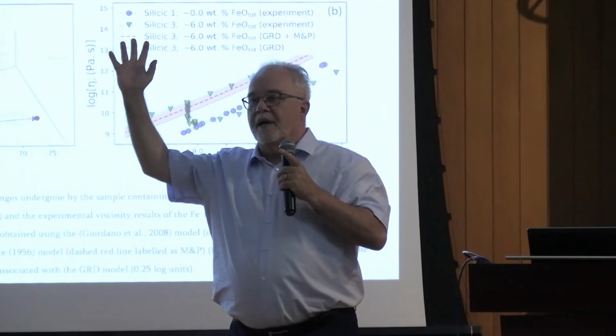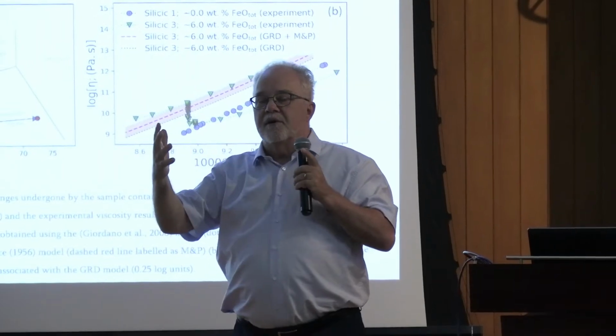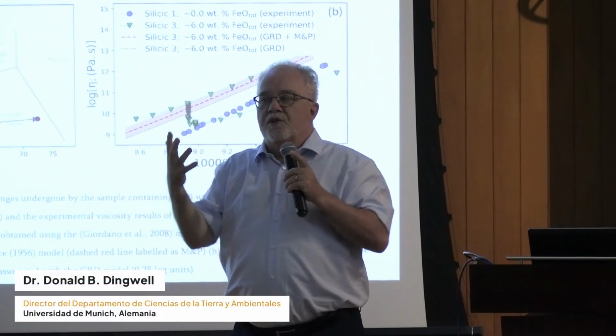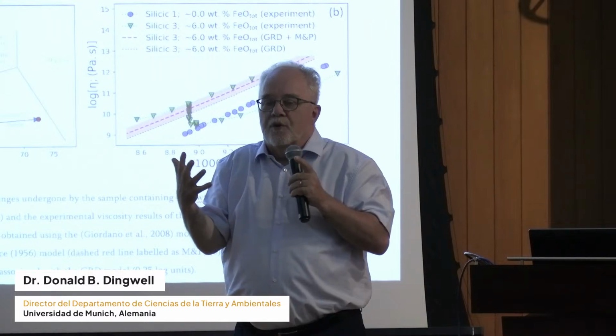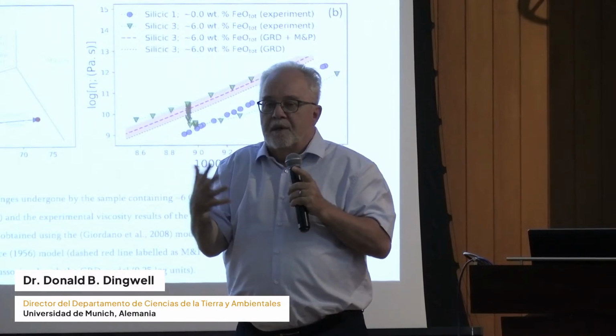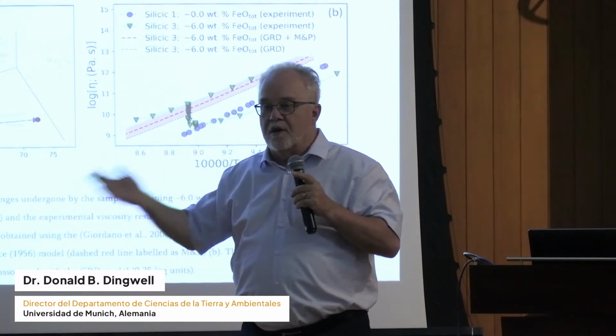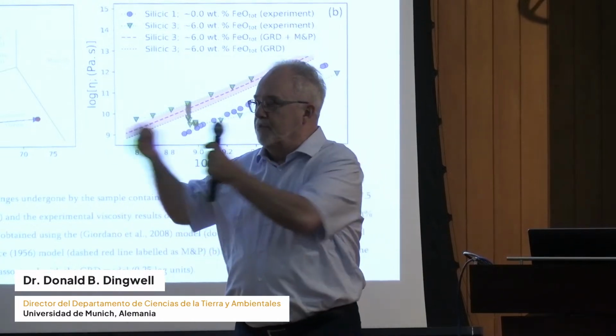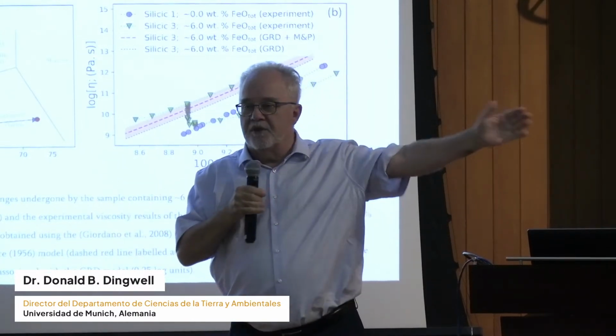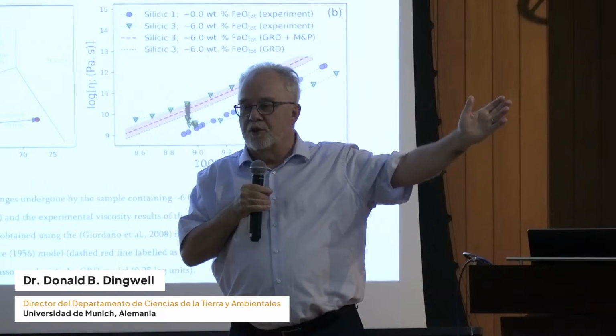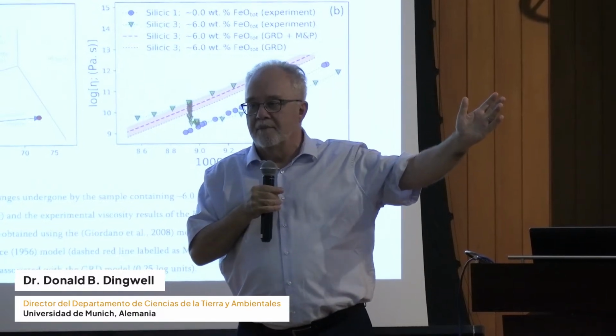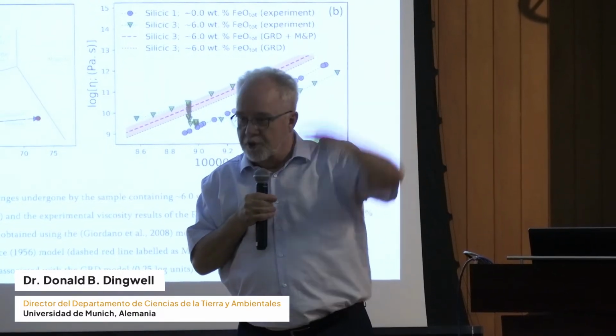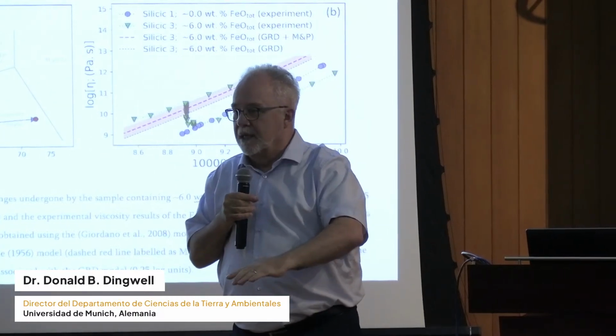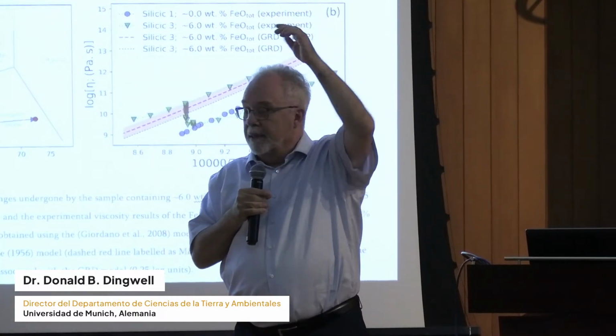Maybe you've sucked all the water out by decompression, bubble growth, fragmentation. The rest of the material is sitting there. The crystallization conditions that were inherent to it are gone because you've removed the water, you've changed the pressure. Suddenly it's jumped sideways with respect to its phase diagram, and it's perhaps undercooled by hundreds of degrees suddenly because the water left. And the water suppresses the liquidus, you see? And if it goes, the liquidus jumps back up again, right?